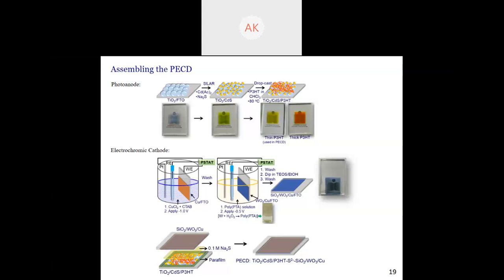So do we actually call them layers, or films, or quantum dots? There are pores. These TiO2 are mesoporous, so these quantum dots grow inside those pores. You can see the yellow color of this quantum dot not only from the top, even from the back of the TiO2 film. So you can see that it has percolated through and is embedded into it.